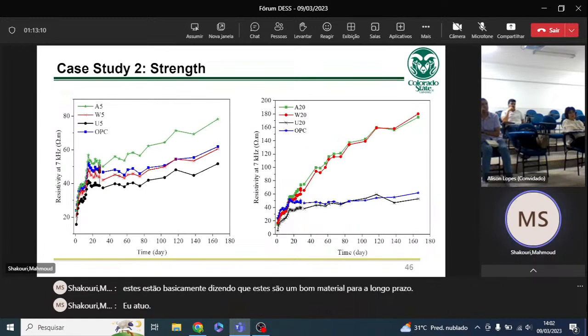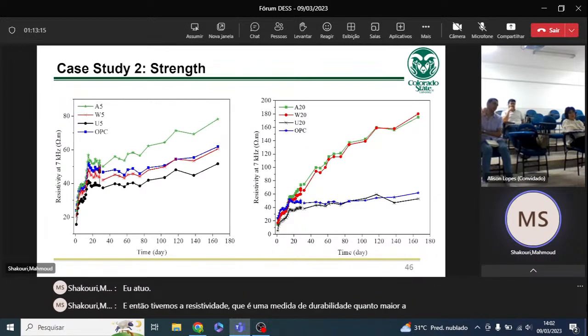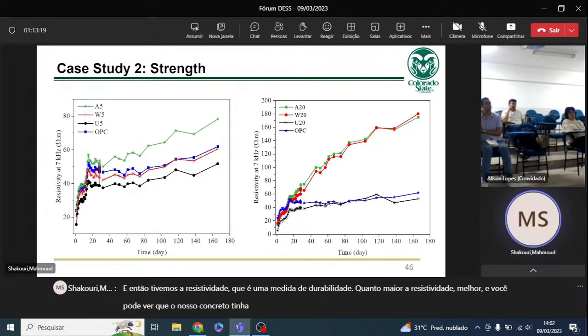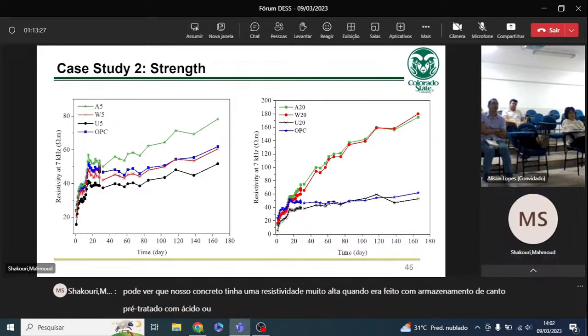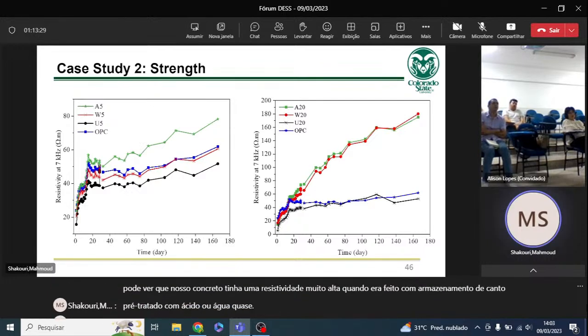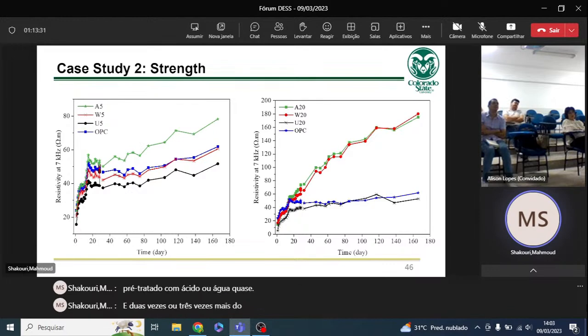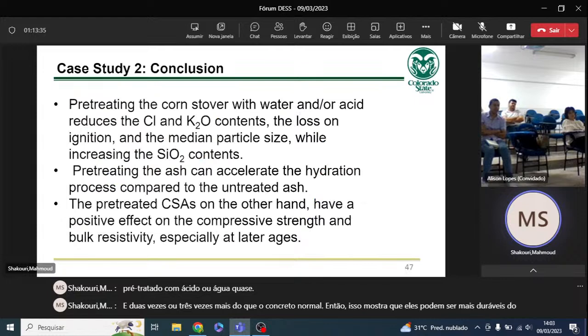And then we had resistivity, which is a measure of durability. The higher the resistivity, the better. And you can see that our concrete had a very high resistivity when it was made with acid or water pre-treated corn stover ash, almost 2 or 3 times more than normal concrete. So this shows that they can be more durable than the normal concrete.